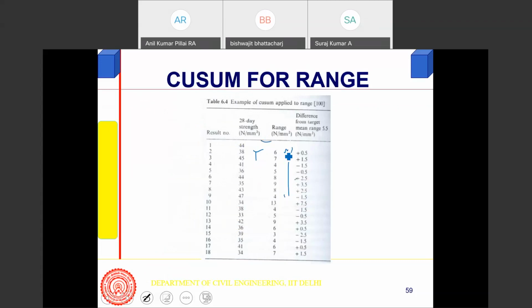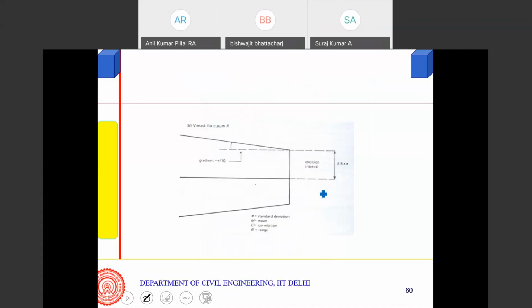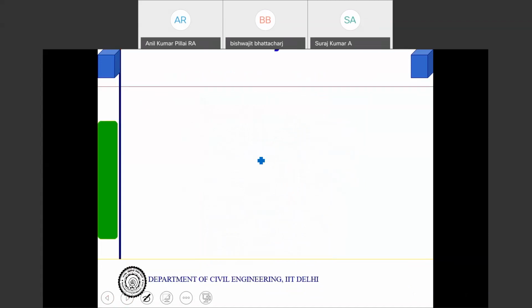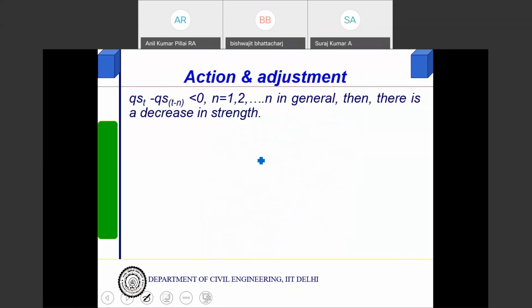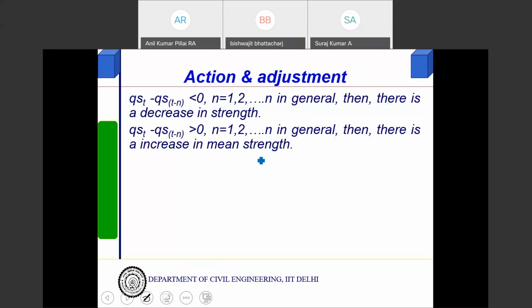So range is the difference between these two, which is 6, and my target range for 5.5 as a standard is to be found out. You can plot exactly the same thing. So is your standard deviation going away? That you can find. But here the V-mask is somewhat different. That's 8.5 sigma by 10. There's a basis for this. So mathematical formulation, if somebody has a question, I can answer this. Write an algorithm for this. Proportion you have to change. Check the correlation. While monitoring, re-establish the correlation, change your results, change the mix, so many things. It can be done continuously, it's not a big deal.